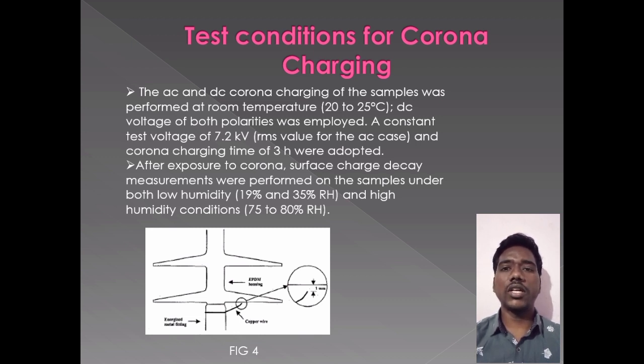To facilitate corona generation, a copper wire of approximately 0.2 mm was attached to the energized metal fitting of the insulator, which is shown in figure 4. With this electrode configuration, the corona discharge path was simulated by a copper conductor whose tip was situated 1 mm away from the weathershed bottom surface.